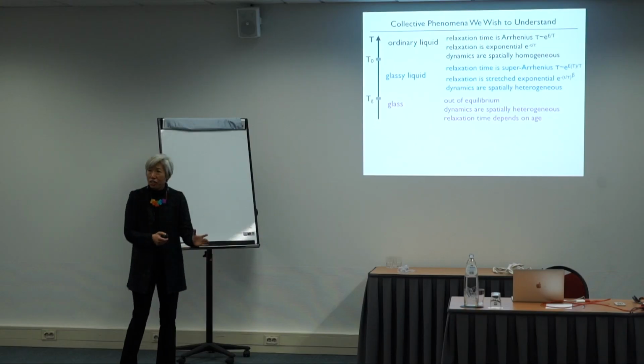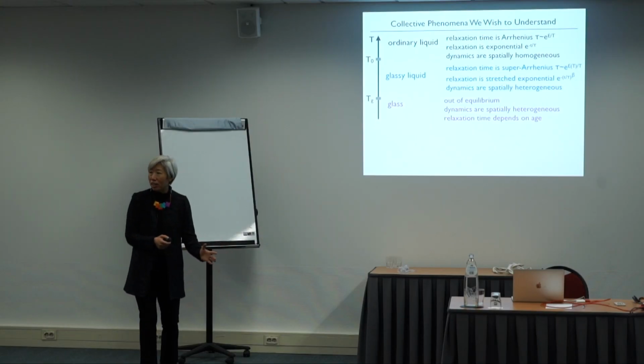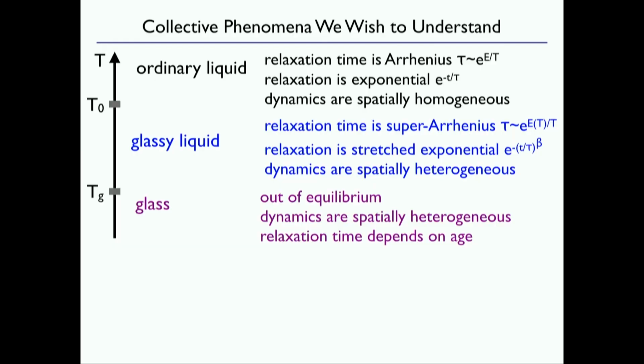Then finally, there's this glass transition, which again is not a transition. It's just when you can't wait long enough. Your stress relaxation time is now longer than your window for waiting, and you fall out of equilibrium. The dynamics are still spatially heterogeneous. And a cool thing here is that what the relaxation time is depends on how long you wait there.